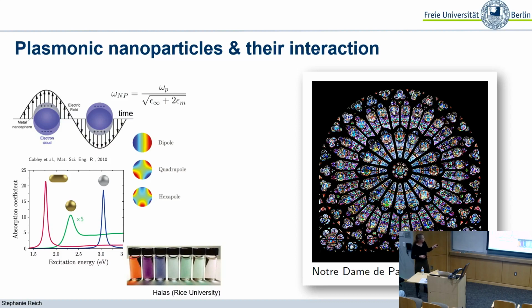And the way in which these gold nanoparticles interact with light is illustrated here. So imagine that you have a gold nanoparticle and an incoming photon. And the photon is shown as an oscillating electric field as a function of time. And when the electric field is pointing upwards, you will have the separation of the electrons and the positive core. And if you wait some more, the direction of the electric field is reverted, and then also the flow of all charges is in the opposite direction. And you can imagine if you drive such a system with the right frequency, you will hit its eigenfrequency and you will get a resonance. And that's called a localized surface plasmon polariton resonance. You can also consider these plasmons, as they're typically called, as excitations of your gold nanoparticles. And there are some ways to write down the expected frequency in a certain limit.